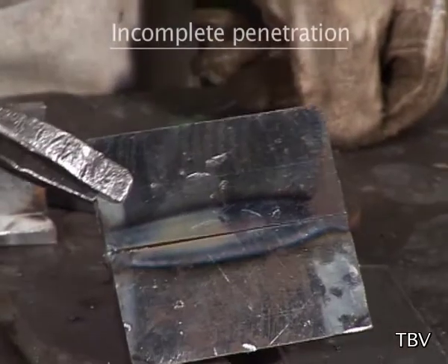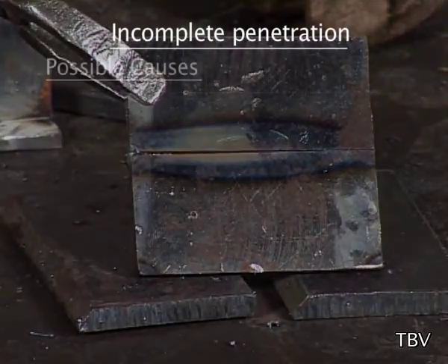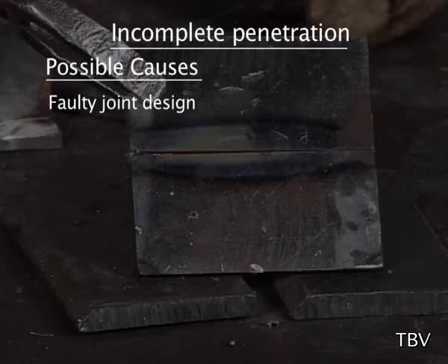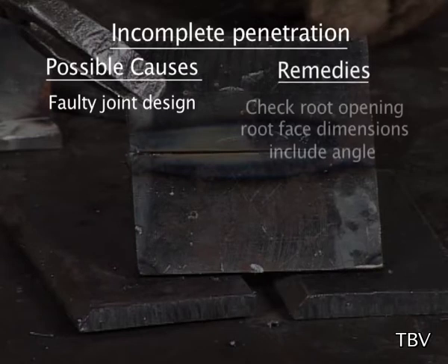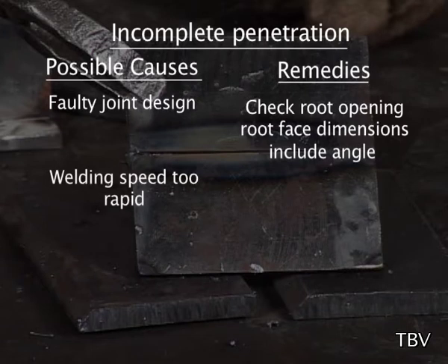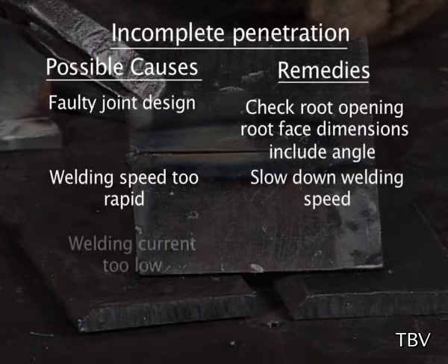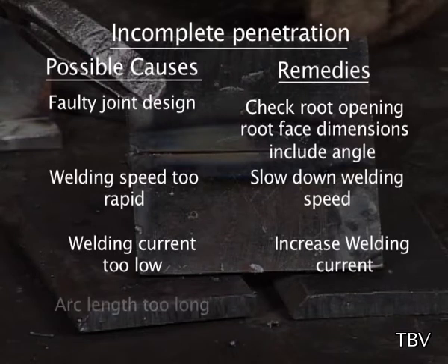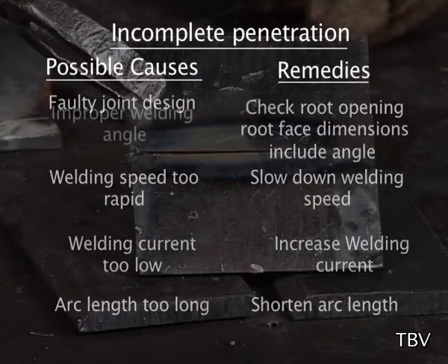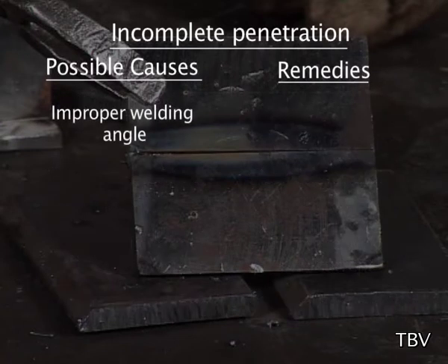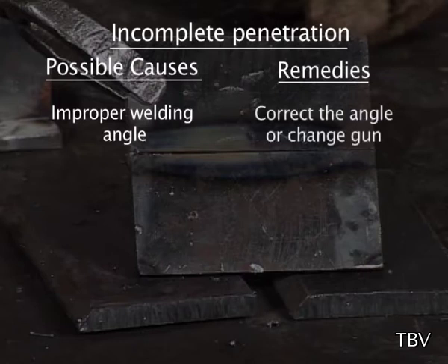Incomplete penetration. Faulty joint design. Check root opening, root face dimensions, including angle. Welding speed too rapid. Slow down welding speed. Welding current too low. Increase welding current. Arc length too long. Shorten arc length. Improper welding angle. Correct angle or change gun.